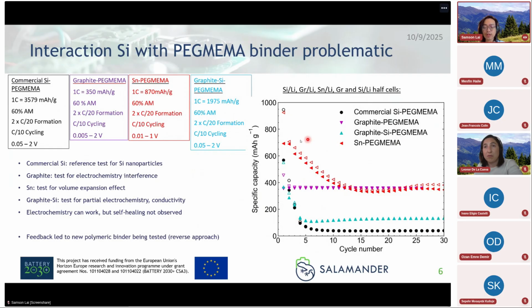So we tried to self-heal some of these polymer batteries, and they didn't really show any difference. Of course, sometimes there's no degradation to heal, let's say. But what we basically have found out is something to do with silicon that's really interrupting this process and just doesn't play nice. So we have actually ended up, through all this feedback, developing a new polymeric binder through this iterative design and testing. And so now we have something that's kind of a different approach.